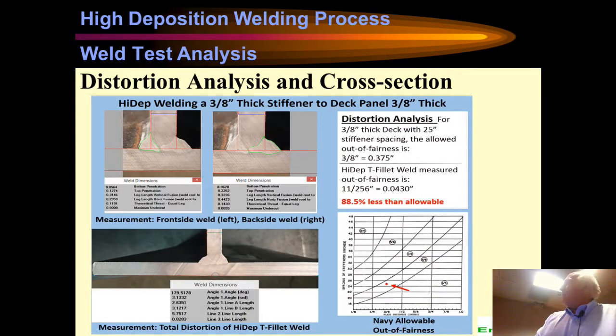All right, so I just brought this up. That little red dot in that chart on the bottom right-hand corner shows a typical spacing, 25-inch spacing with 3/8 inch thick deck plate, and that's the Navy allowable, the amount of out of flatness the Navy allows them to hit, which is actually 0.375 inches between those two 25-inch spaced stiffeners, and our distortion instead of 0.375, we're 0.043. So we're 88.5% less than what the Navy even allows.